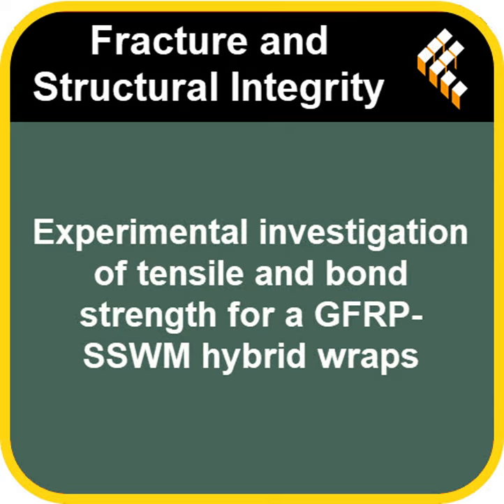Okay, now let's talk about something you mentioned earlier, the glue, the epoxy adhesive. How much did that matter? Oh, it mattered a lot. The choice between Sikadur 30 LP and Sikadur 330 had a really significant impact. It wasn't just a minor detail. And it seems like one generally performed better, Sikadur 30 LP, especially with the hybrids and the steel mesh. That's right. Generally speaking, Sikadur 30 LP resulted in higher ultimate load capacity and also higher displacement, more ductility. Particularly for any configuration that included the SSWM, for instance, that GS specimen. With Sikadur 30 LP, it carried about 8.7%, almost 9%, more load than the exact same GS wrap using Sikadur 330. 9% just from changing the glue.